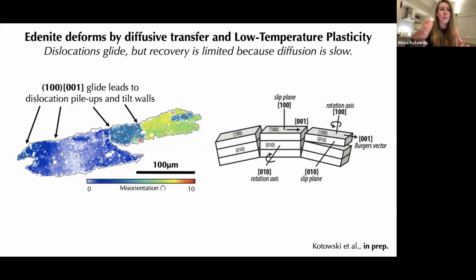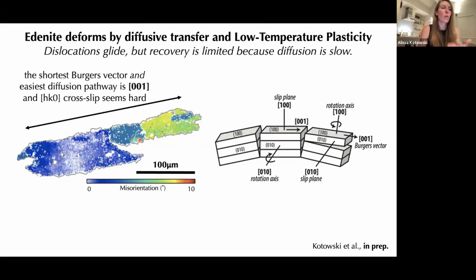But then if these dislocations are getting stuck here, what happens then after that? Well, under low temperature conditions, diffusion is relatively slow. So recovery is probably limited. And the dislocations can glide along the 001, the shortest Burgers vector, and diffusion also happens along this same direction. We know this because of the direction of the growth zoning in the metamorphism. But this diffusion doesn't actually help the dislocations because they need to climb in another direction, away from 001, or they need to cross-slip or annihilate in order to achieve recovery. But diffusion or cross-slip in other directions seems to be very, very hard.